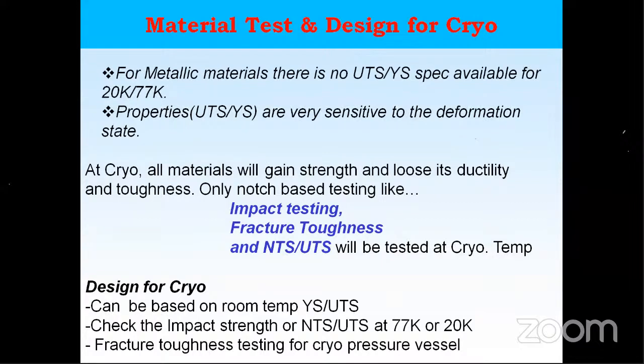Recently, when I was in LPSC, there was a query. Normally we don't use 7075, which is an aluminum zinc magnesium alloy, a high strength alloy, in low temperature applications because we have 2219 and other materials available. But somehow people wanted to use this material. Then they asked me, and the first test I did was impact testing. I found it had a very good value. Okay, you can use it safely, there is no issue. Like that, the first screening is to go for impact testing.